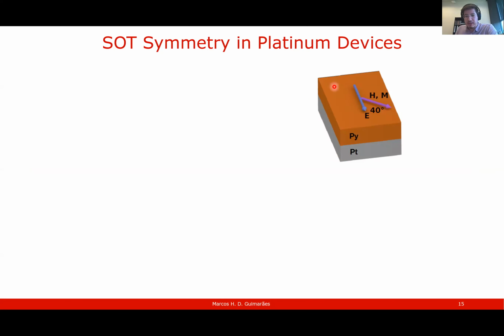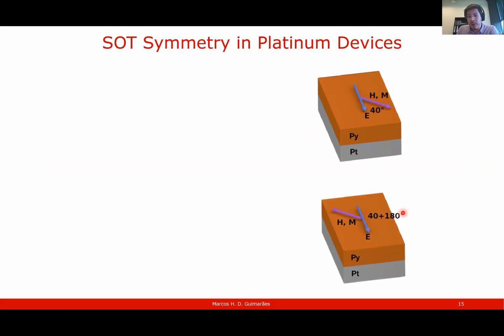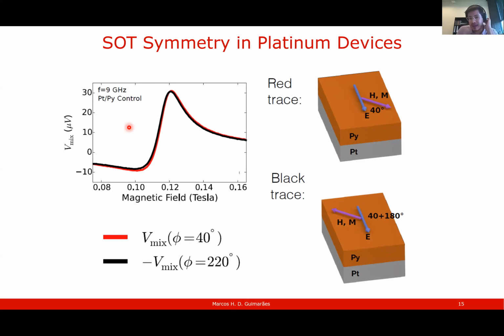So if you take the basic system, the standard in the field, platinum and permalloy. Permalloy is a ferromagnet. Platinum is your spin orbit metal. You apply an electric field or a current through it, and you have the magnetization, let's say, pointing at 40 degrees with respect to the current that you apply. This is fixed by an external magnetic field H. Now, if you reverse the magnetic field, the magnetization will reverse. And what you get, up to a minus sign, is that the resonance shape from the spin torque ferromagnetic resonance for a fixed frequency looks like this. If I apply the magnetic field at 40 degrees, you can see it here in red. And if I reverse the magnetic field, so now apply it at 220 degrees, then that's the curve in black. And they overlap. They fall exactly on top of each other.